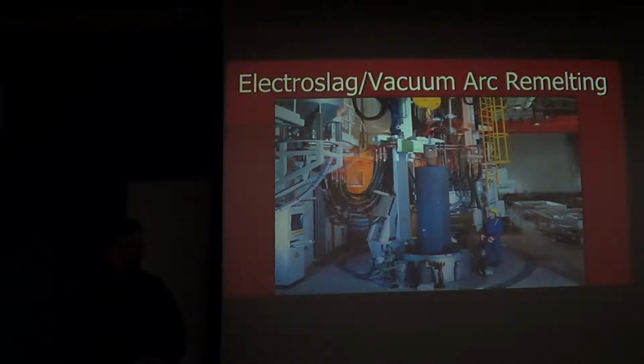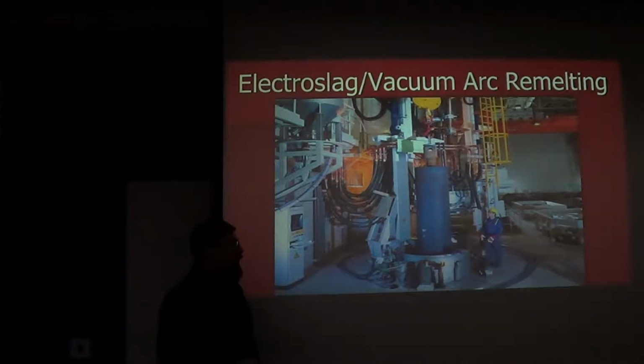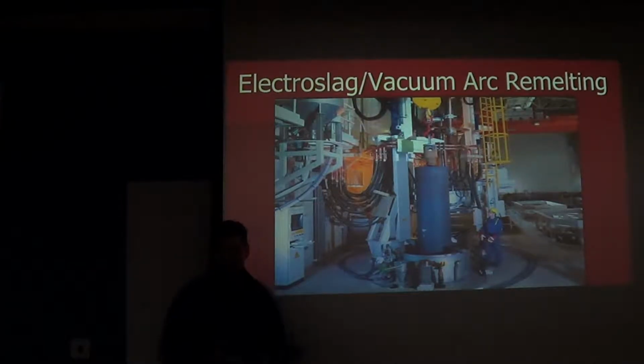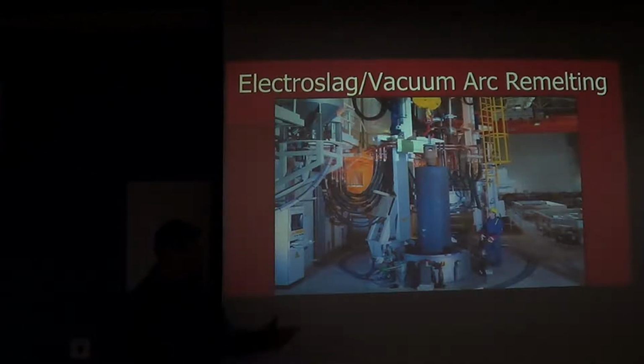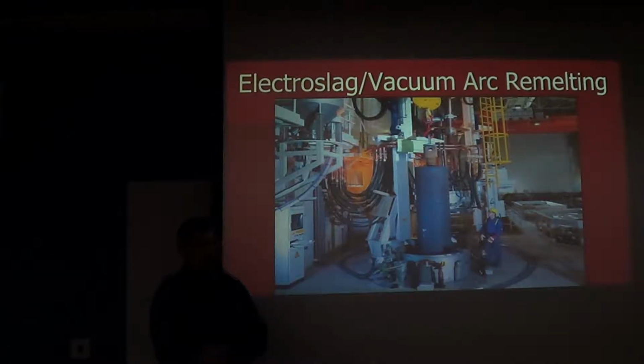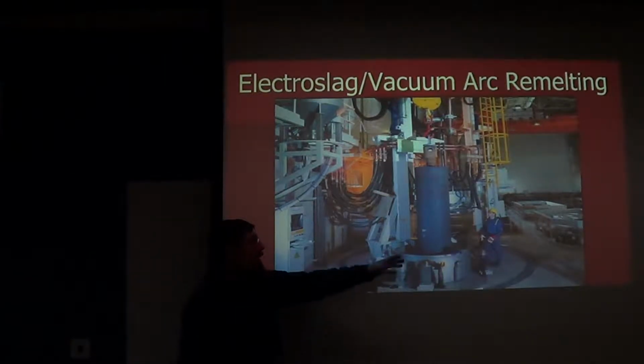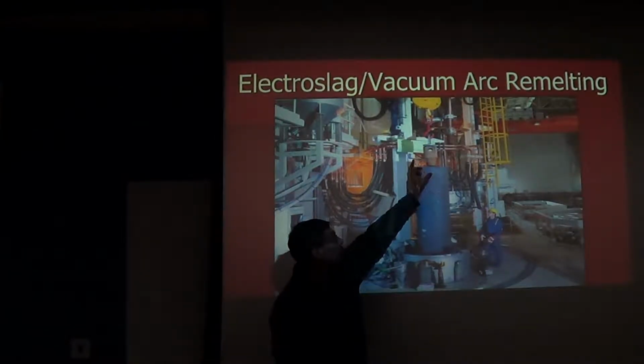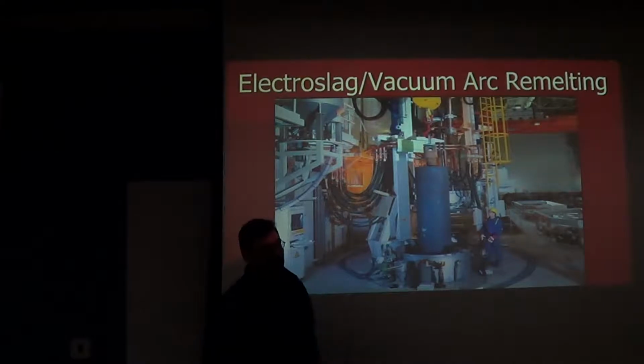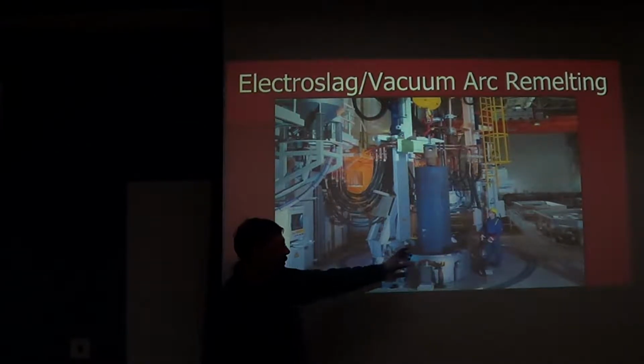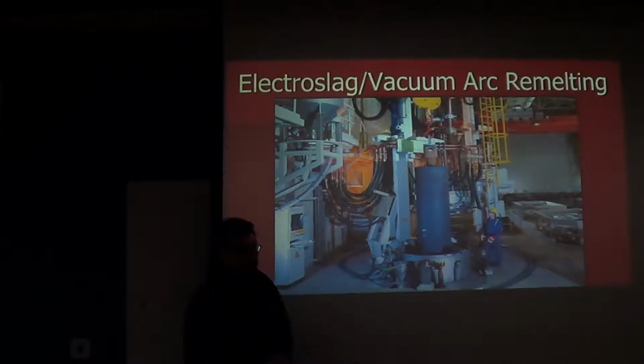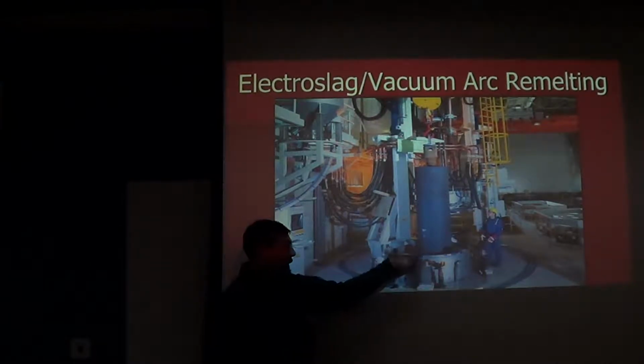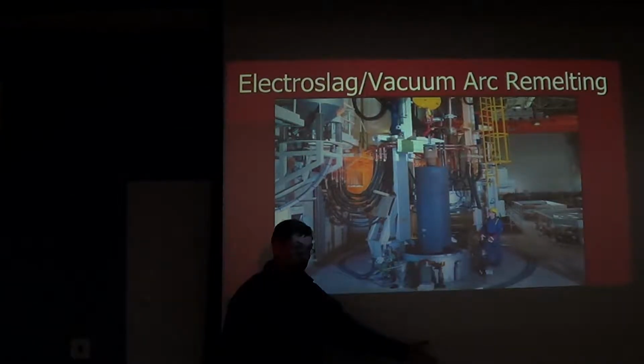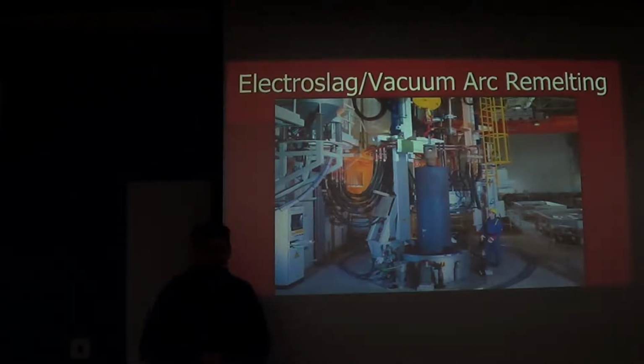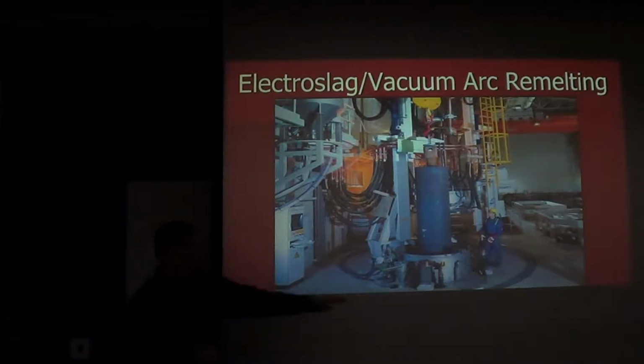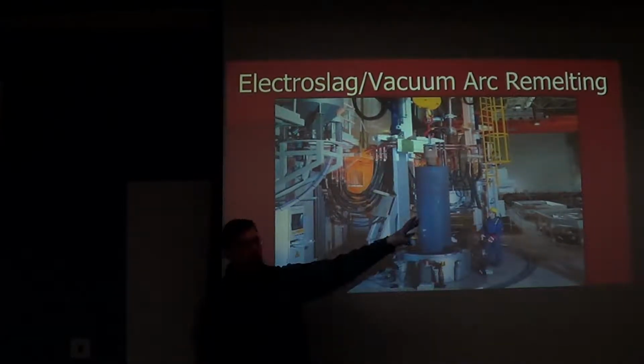We can take the output of that process, an ingot, and we can turn it essentially into a giant welding electrode. If anybody's had a chance to do any stick welding in particular, this is basically that, scaled up to a massive level. You take the ingot, you weld a fixture to the end of it so that you can bring in a power source, and then you put it into a large water-cooled copper mold. And what happens is you strike an arc on the bottom between the ingot and the bottom of the mold. And it's exactly like welding in that you're melting from one end to the other, but that happens over a long period of time.